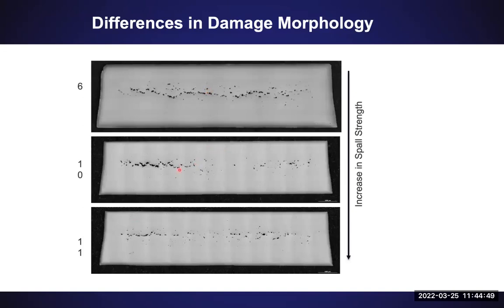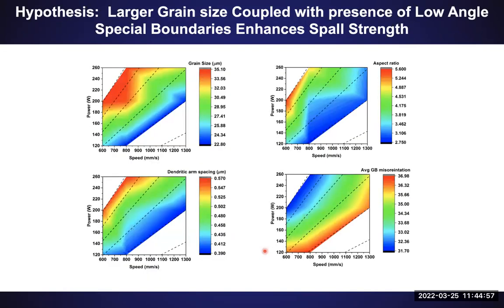you can see that the total amount of damage did indeed go down, but we wanted to try to understand why that is. So we did a deep dive where we plotted parameters like grain size, the aspect ratio of those grains, dendritic arm spacing in these samples, and average grain boundary misorientation in the samples. And again, these are plotted as a function of laser power and laser speed. One thing we noticed is that the samples in the sweet spot we're looking in tended to have a large grain size,